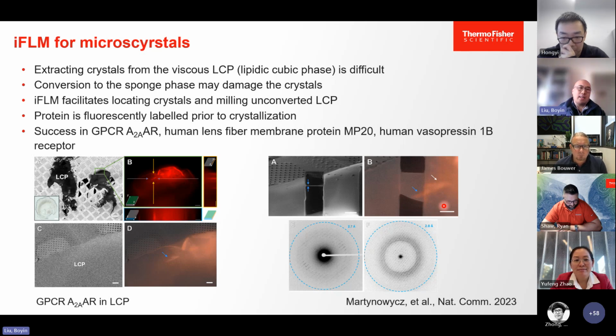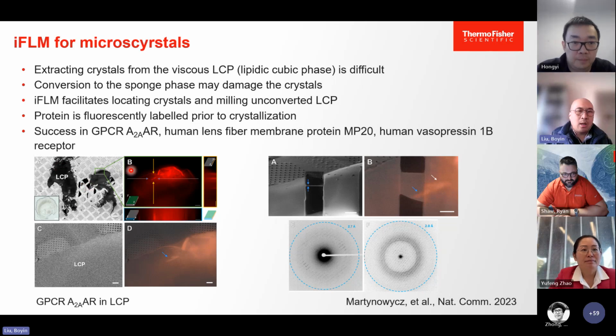So what the authors did was to fluorescently label the protein before crystallization, and then use plasma FIB to mill down the crystals. They already have lots of success in samples like GPCR, MP20, and human vasopressin 1b receptor. So this is an example of a GPCR embedded in the thick LCP. You can see on the grid, there's completely no topology to tell you where the crystal is. But after you switch on the iFLM, you can see the glowing crystal here.